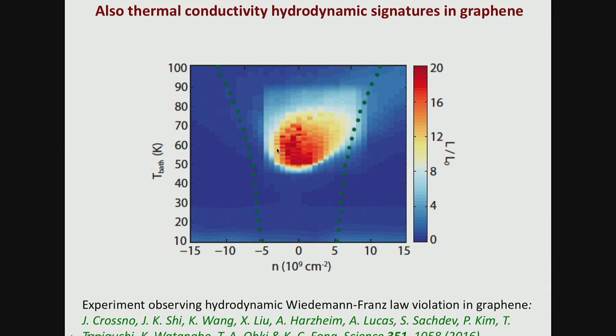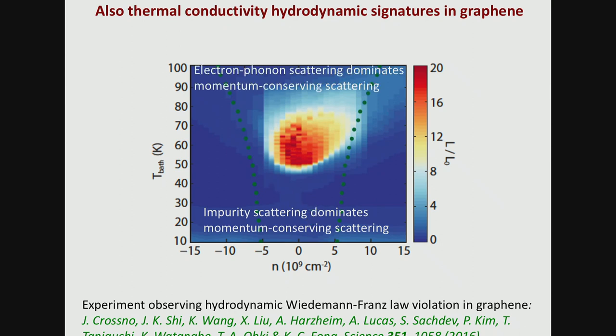And this then helps to illustrate some of the more general problems with the experimental field. If they go down to lower temperatures, impurity scattering, well, when I say impurity, it's this charge puddle scattering that they get. They get static disorder, which kicks in and kills their observability of the Wiedemann-Franz law violation. They go to higher temperatures, electron-phonon scattering comes in and dominates the momentum, and that momentum-relaxing electron-phonon scattering dominates the momentum-conserving scattering. So they actually have this hotspot for the observation of what they attribute to a hydrodynamic violation of standard transport. And this is, again, general to hydrodynamic experiments. It can be that you need to find just the right temperature and density window to see the effects that you're looking for.